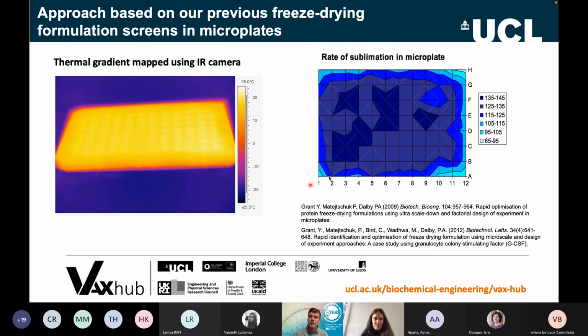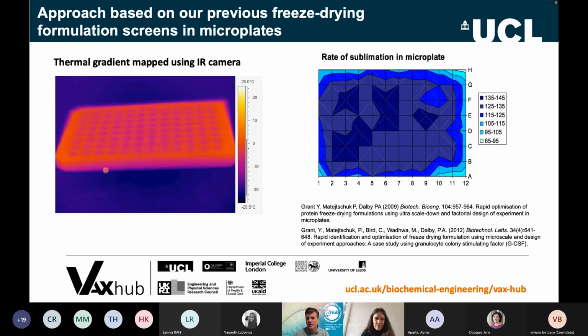So that's one reason. The other is that you'll notice, if I could play this video again, it isn't perfect. You do get some edging on the temperature. You can see it's like a hot potato effect where it cools into the middle. So you do get different thermal conductivity in the middle compared to the outside, right? Because you've got contact between these wells, which are a similar temperature, but not being equilibrated to the outside temperature quite as easily, other than through the top and through the shelf. So there is a bit of a thermal distribution across it, which may well give some of this difference in sublimation. One hopes that you're removing the vapor quickly enough that the vapor pressure above it isn't an issue, but I think it is.